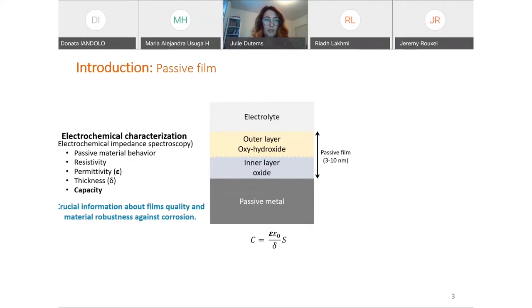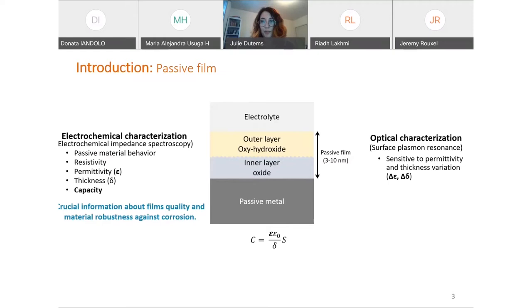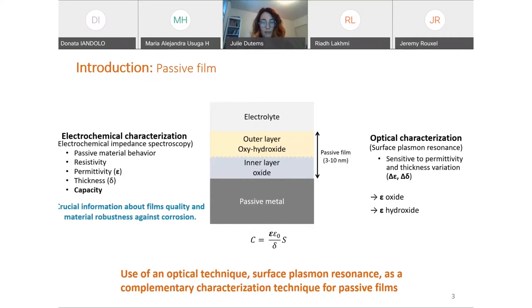The idea behind my project is to use an optical characterization called the surface plasmon resonance to characterize this passive film. Surface plasmon is very sensitive to permittivity and thickness variation. And this combined technique, surface plasmon resonance, aims to be a complementary characterization technique for passive films, to help to decorrelate, to add more information about this passive film, just for example, to have the permittivity of the inner layer of oxide, or the outer layer of hydroxide.